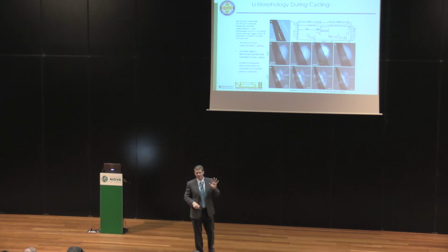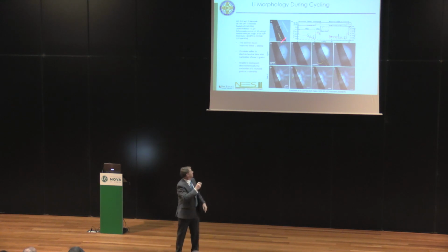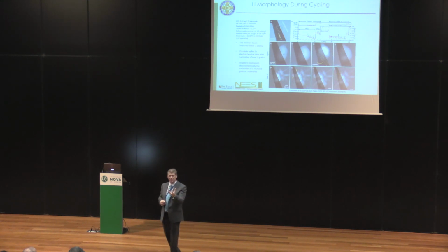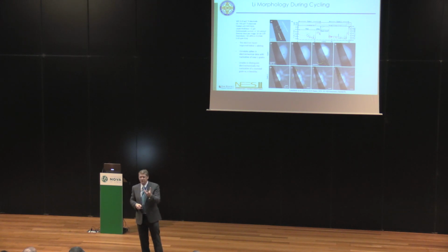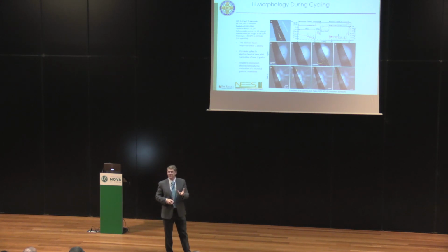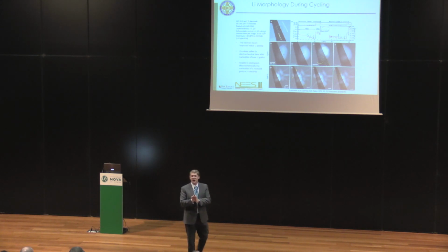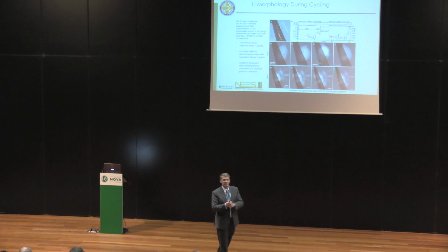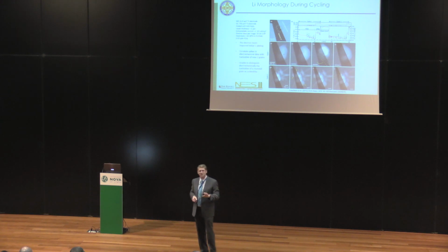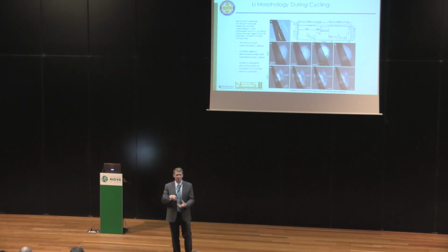In a lithium battery, there is no anode material. The lithium is directly plated onto your charge collector, and that's what you have here. This is a glob of lithium metal that's been directly deposited. So this is a lithium battery. And why do you want a lithium battery versus a lithium-ion battery? Well, energy density. If you can just plate lithium, you're going to have a much higher energy density battery than if you have to insert it into another material. Typically. There are examples, such as silicon, where if you insert lithium into silicon, that energy density is actually higher than pure lithium, interestingly enough.